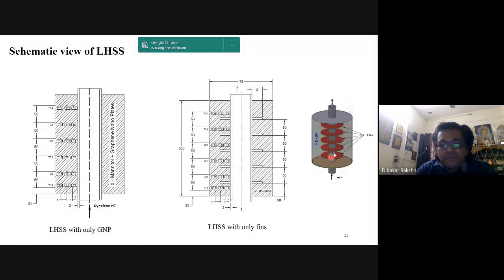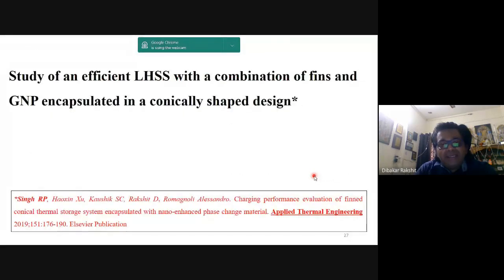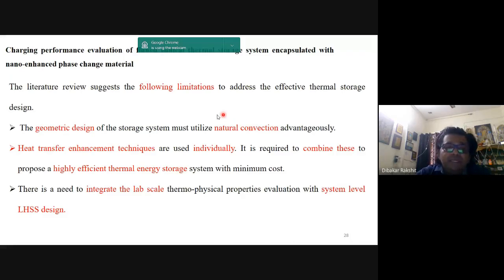The next was to see the efficient utilization of this latent heat energy storage system in combination with fins by incorporating the shape factor. So till now, what we were doing was a cylindrical structure which we have designed, but ultimately we started seeing whether there can be any other shape in which the combination of conduction and convection happening through this thermal energy storage battery can be enhanced. Of course, a conical shape was introduced, sometimes called the frustum of a cone. And then we again started seeing the same type of effect which we were looking for in that cylindrical battery. And these were some of the research gaps, like the geometric design of the storage system, which means utilizing the natural convection advantageously, has not been explored.